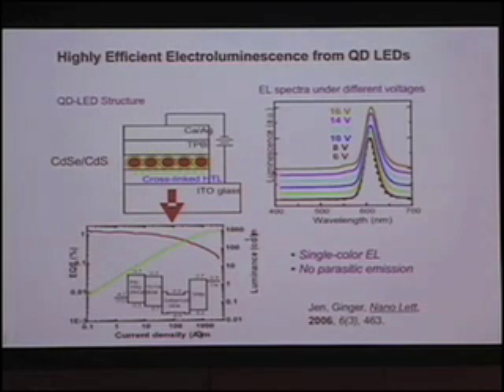Based on that, we demonstrate one of the very challenging tasks in LED, which is to make the quantum dot-based LED. This is a solution-processable quantum dot LED. You can base it on your cross-linked hole transport material. Now you take quantum dots and spin coat one monolayer of quantum dots on top of this. Depending on the concentration, you can manage to have only one monolayer, about 5 nanometers. Then you evaporate your electron transporting layer on top of that, so you build your device on that.